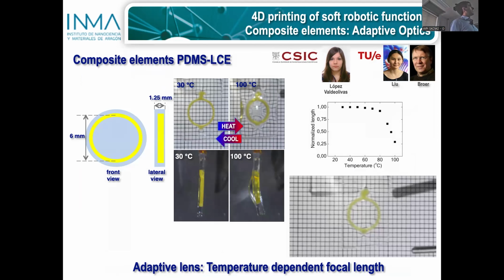We have also embedded these materials in PDMS, in other elastomers. Here you have a ring of our material embedded in a slab of silicone, of polydimethylsiloxane, and on heating, due to the asymmetric positioning of the ring with respect to the PDMS, we have buckling. This compression causes the PDMS to buckle out of the surface and generate a lens, making the shape of a lens whose focal length depends on the temperature.